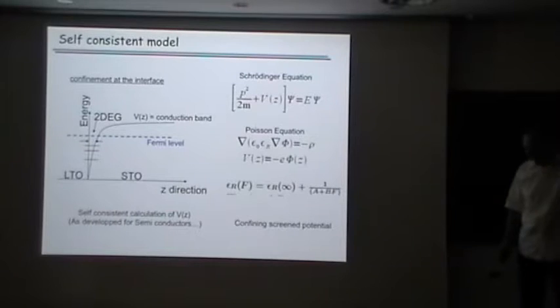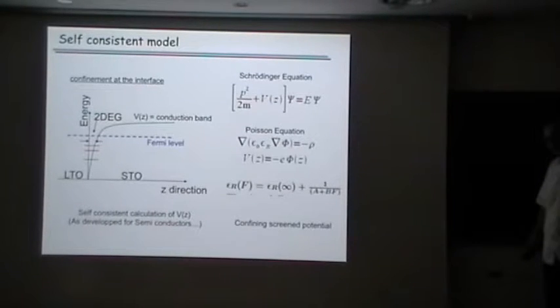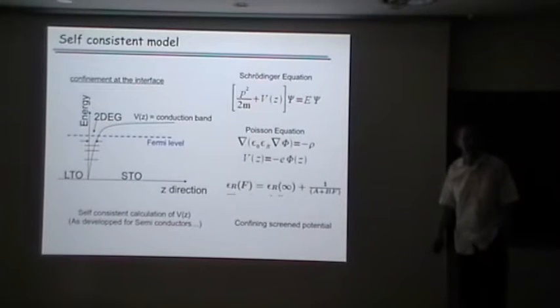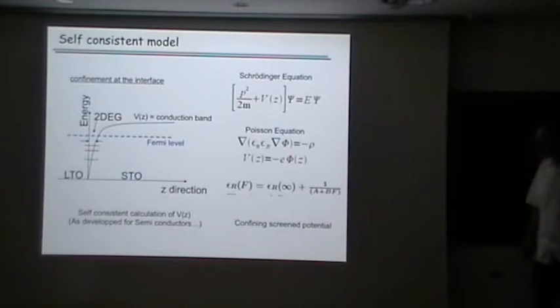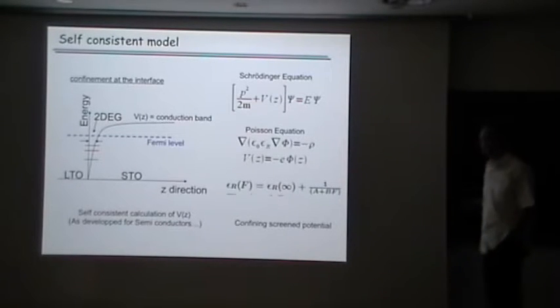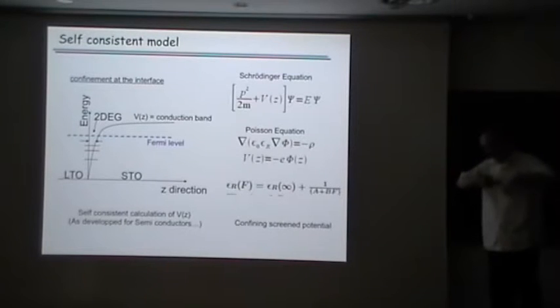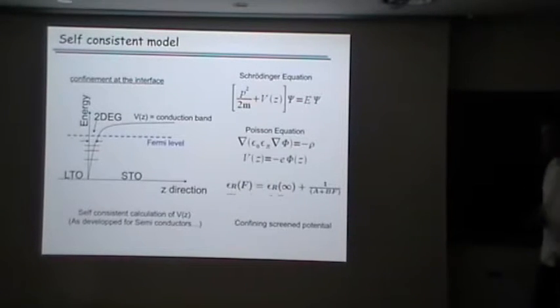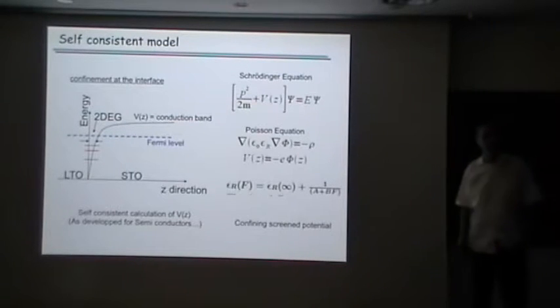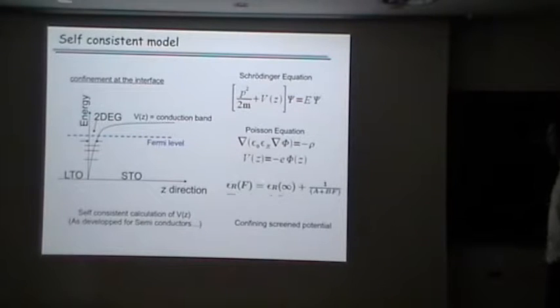And instead of making a very complicated analysis in terms of quantum criticality, we just used a very simple argument to see what's going on in the system when we put just a back gate voltage. As I mentioned to you yesterday, it's important to model the interface. There are a lot of models in the literature. We made our own models, very simple. So you have just a Schrödinger equation and the Poisson equation here. Of course, we have to use the highly nonlinear and temperature dependent dielectric constant of strontium titanate. And then we also have to screen the potential. We put everything together and we compute this system.